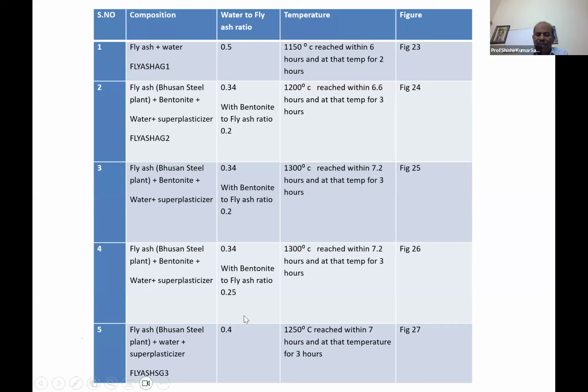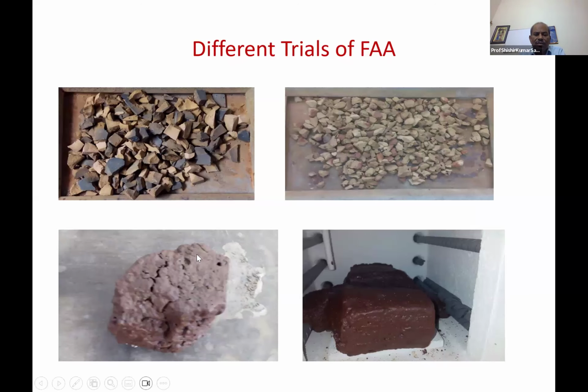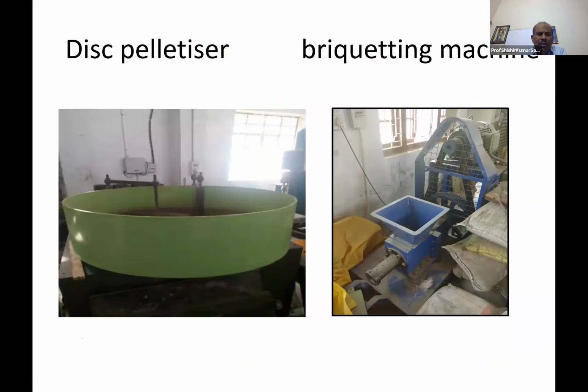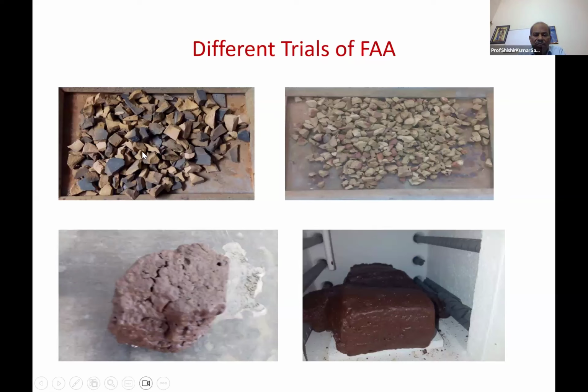So this way we have manufactured this one, and bentonite. Both the processes, with sintering temperature at 1250 for 7 hours, and at 1250 for 3 hours, give us the best aggregate. You can see it here. Different trials we have done. This was the best aggregate.